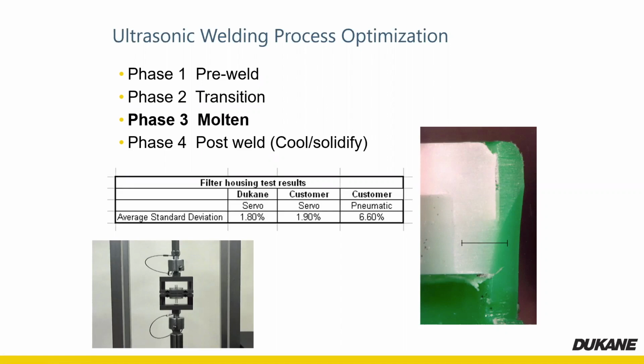And we've repeated this time and time again, but this was one that the customer was willing to do for us to gather this information, to be a little bit more objective. And what they found, and what we've seen time and time again, is these pull test standard deviations go from 6% standard deviation on pneumatic, which is not uncommon, down to 1 to 2% on servo. So your pull strength becomes extremely consistent. You do not have the variability in that pull strength anymore. And I like to say with the servo, we've basically eliminated all of the variability of the process itself. All that's left is the variability of the plastic, and I can't do anything about that. So that's on your molder.